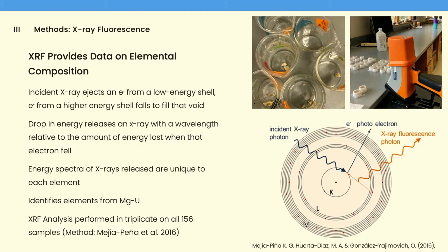Our X-ray fluorometer identifies elements from magnesium to uranium, so not the entire periodic table, but a good portion of it and the portion concerning the elements I'm interested in. And I used X-ray fluorescence in triplicate on 156 samples that are all contained in those tiny little cups. That large ray gun looking thing is the X-ray fluorometer itself, and the little white cups next to it are the powderized sediment. I dried that sediment in a drying oven, powderized it to be less than 61 microns, and then analyzed it using the XRF.